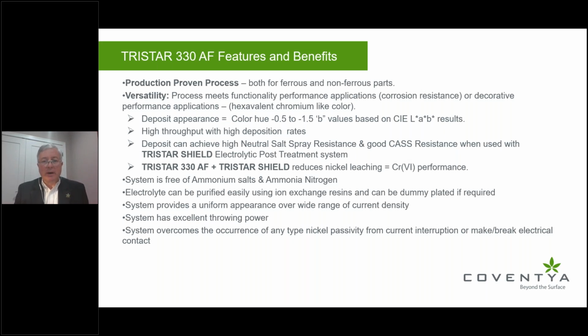We can plate over a very wide range of current density, excellent throwing power, and one of the real big differences between trivalent technologies and chrome 6 is the fact that you can overcome weaknesses when you have problems with rack tip connections on parts. Nickel passivity is stopped. You can do current interruption in some applications, and you don't see a negative effect on the deposit like you would with a chrome 6 system. So a lot of advantages of chrome 3, and that's why it's really important to try to adapt these technologies to replace chrome 6 wherever you can.